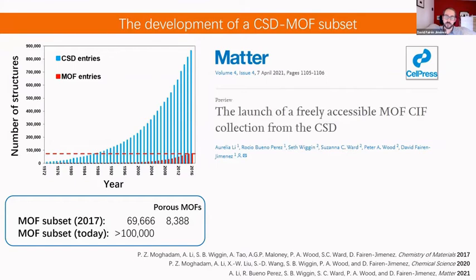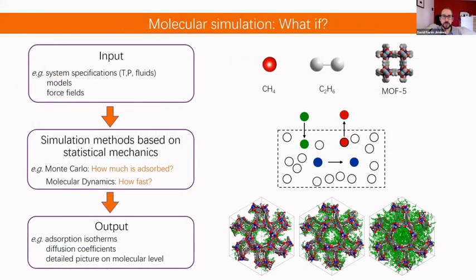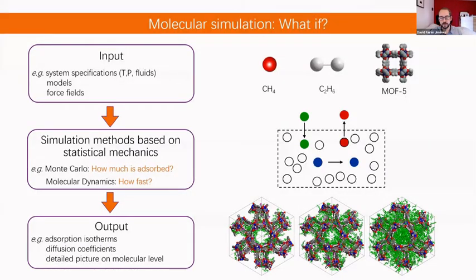And now, once we have these MOFs, we can start using molecular simulations to predict the performance of materials. We need some input information for the models: the molecules we want to simulate and the crystalline structures, and then we can use different techniques. We can use Monte Carlo to answer the question, how much gas can be adsorbed in one specific material? If we have a mix of gases, what is going to be the selectivity? Whereas we can use molecular dynamics to answer questions about kinetics. And the output information we get is going to be adsorption isotherms, diffusion coefficients, and a very detailed picture at the molecular level of the adsorption process.